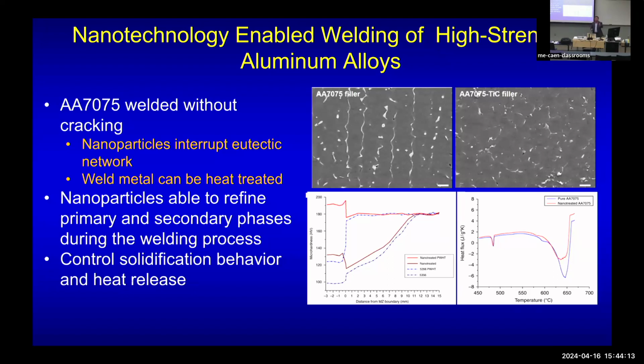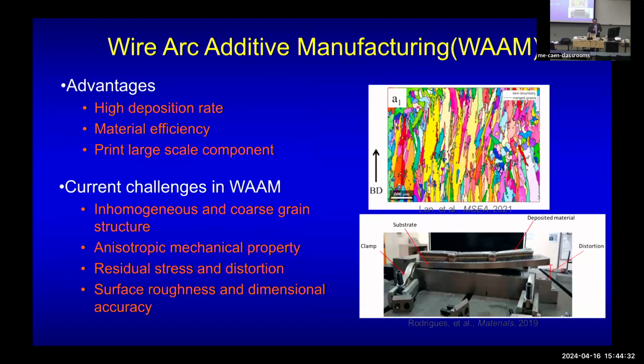And by that, you pay the penalty in strength. Normally the strength reduction goes almost to a 30% sacrifice, a penalty. But with our nano composition, if we go to heat treatment, we can recover 100%. So this is one thing for the welding. And obviously, welding and additive manufacturing are almost like twin brothers. You can do welding, you can do additive manufacturing.